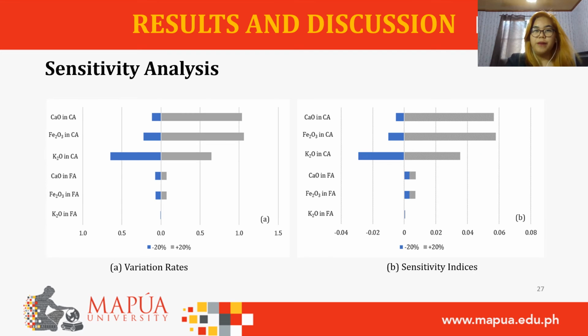Because of the various compounds present in the aggregates, a sensitivity analysis was done to determine which compound greatly contributes to the MAC of the sample. The compounds lime, iron oxide, and potassium oxide in coarse and fine aggregates were investigated, and their variation rates and sensitivity indices are shown in the slide. As expected in both parameters, iron oxide had the highest impact on the MAC, mainly because of the iron having the highest atomic number among all the input elements.